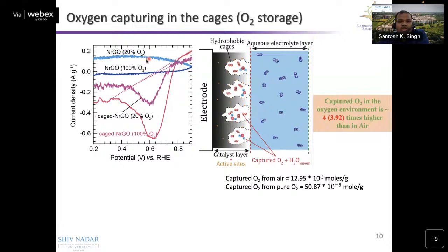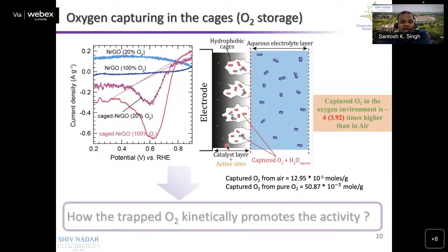So based on these findings, we have developed one model here. What exactly is happening in the catalyst layer? When the catalyst has a hydrophobic cage structure, most of the oxygen is captured from the electrolyte solution into the cages, and it is supplied to the catalytic active sites regularly. After the reduction, these cages act as a pumping mechanism. Once this oxygen is finished, oxygen is again captured from the electrolyte and supplied to the active sites. This is how hydrophobicity plays a role, and we continuously get higher activity out of it.